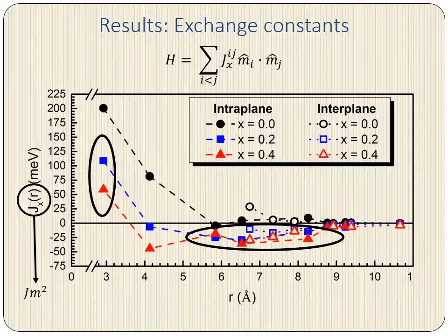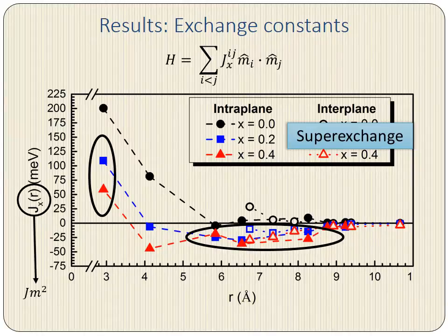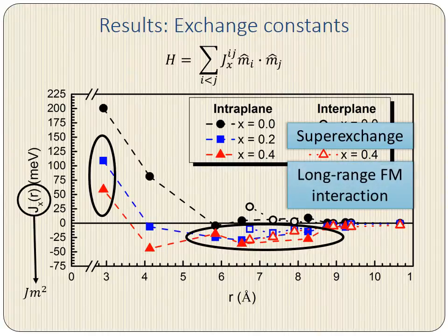This indicates a competition between a short-range superexchange interaction, which is providing that antiferromagnetic coupling, and also a longer-range ferromagnetic interaction, which can be identified in the end as an effective double exchange interaction. I'll explain what I mean by that in a couple of slides, but first, we actually now have enough information to discuss the puzzling reduction of the manganese moment in experiment.